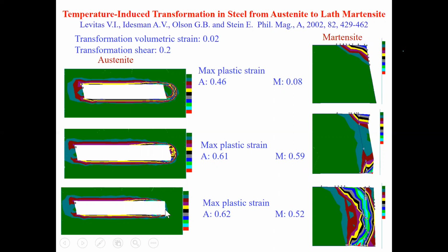And this plastic deformation drastically affects the stress field here and arrests the phase transition. So this shows that even under hydrostatic condition, or even without any stresses, plastic strain still occurs, and it strongly affects phase transformation.